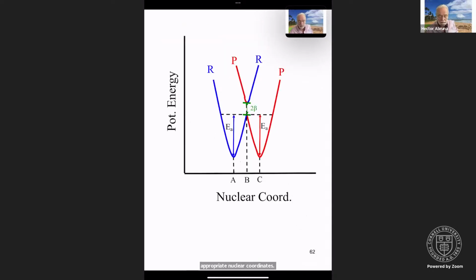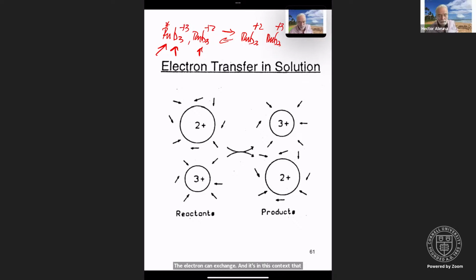And it's in this context that we will talk about Marcus' theory of electron transfer, and his theory, in the classical limit, tells you how you reach the transition state. How do you get to that intersection region? By changes in the nuclear coordinate, changes in the polarization. The other thing that you will notice here is because the charge density on the 2 plus is smaller, the solvent dipoles are less polarized here than in here. So you're going to have to take into account changes in metal-ligand bond distances, changes in the polarization of the solvent. And this will in turn contribute to the activation energy, which is at the heart of the Marcus theory, which in a real sense is sort of a classical theory, except put in terms that are tractable and that we can actually do something with.